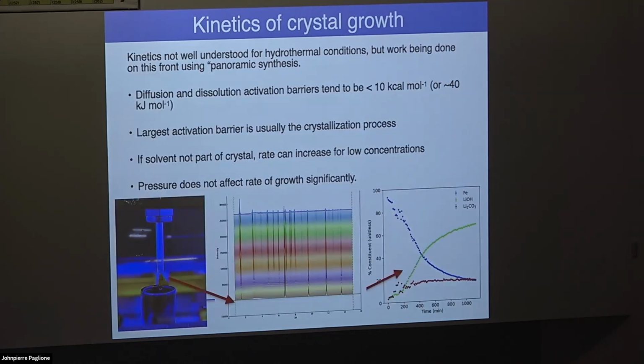So again, I mentioned the kinetics of crystal growth. This is one of the reasons that hydrothermal synthesis is dubbed a black box reaction. You put everything in, you put it in the oven, forget about it until you have to go collect it, take it out. You have no idea what happens in between. If we're trying to synthesize metastable states, what actually happens in between is really interesting for us because we want to know how we can use that kinetic pathway to maybe form other compounds.